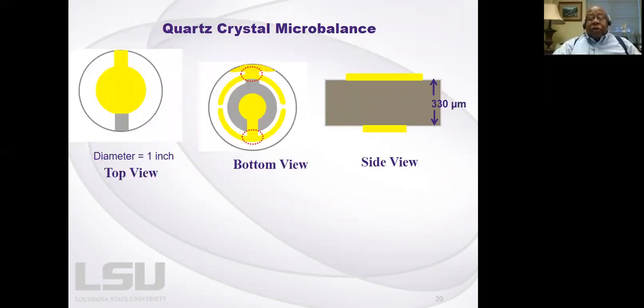So here's the quartz crystal microbalance. Top view, the yellow is just the gold surface, and the bottom view is also gold. And in between, over to the right, we have the crystal sandwiched between those gold surfaces. The crystal in a quartz crystal microbalance is typically quartz. You apply a sinusoidal voltage on those gold electrodes, and you get the vibration that I talked about.